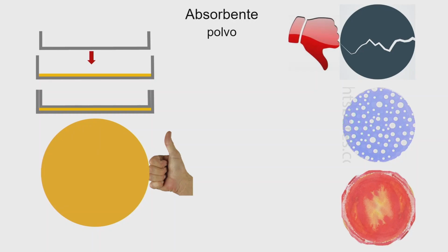So that what you get for any part of your absorber, it's bringing to you the same information, okay? Once I visited the laboratory of C.L. Chin in the University of Baltimore, and the first thing he told me is holes kill your spectrum. And this is very true, because if you have holes in your absorber, then gamma rays will pass freely and contribute very much to the background.